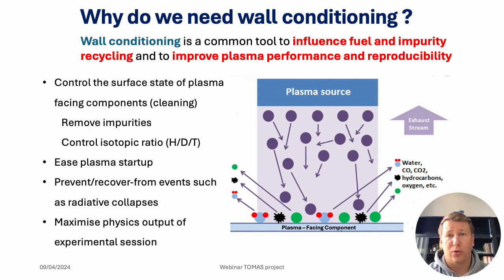It can lead to a few adverse effects. For example, if the walls are dirty, containing a lot of trapped impurities, the escaping charge exchange neutrals can cause their release into the plasma volume. Heavy impurities inside the plasma radiate the power faster than we heat the plasma, leading to radiative collapses, sudden discharge termination. The fuel itself can be stored on the wall surfaces. When it's released during the consequent plasma discharges, it makes it hard to control the fuel species ratio and the plasma density. All these adverse effects significantly reduce the plasma performance. To avoid this, we need to clean the walls of the fusion reactors before operation by using various methods called wall conditioning.